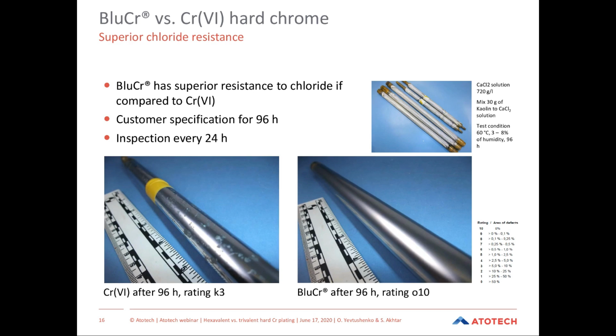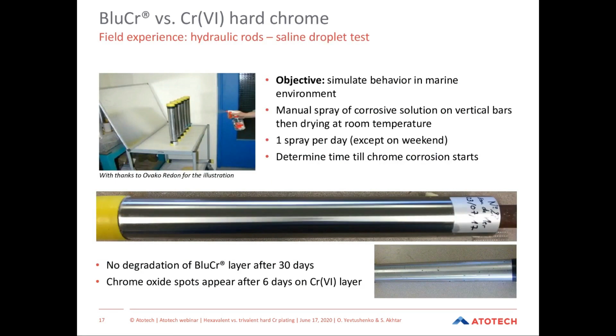So why does this happen? Also because the chromium layer which we deposit from blue chrome is not pure chromium, but also contains a small quantity of carbon inside. And that's our explanation for why the corrosion resistance is better for chlorides.